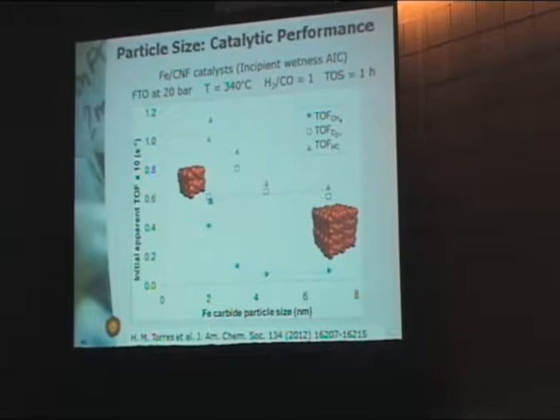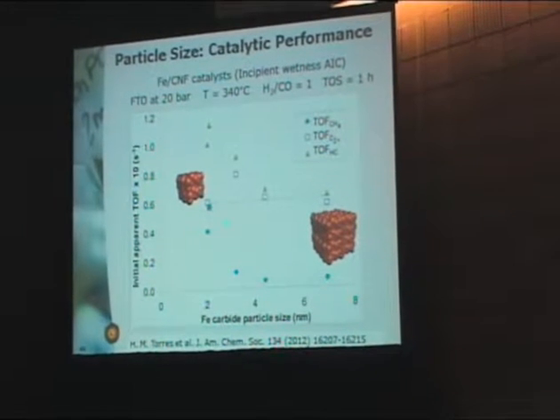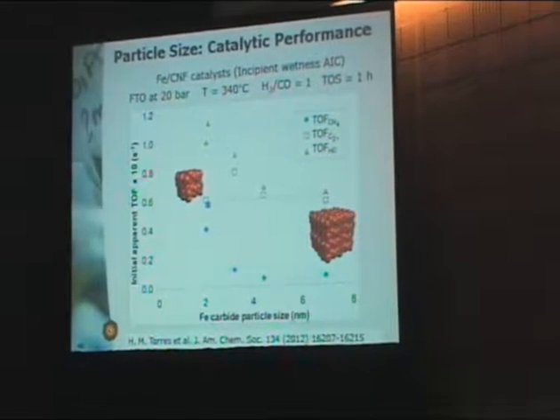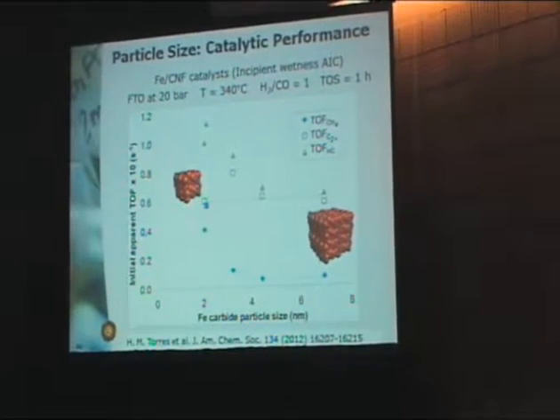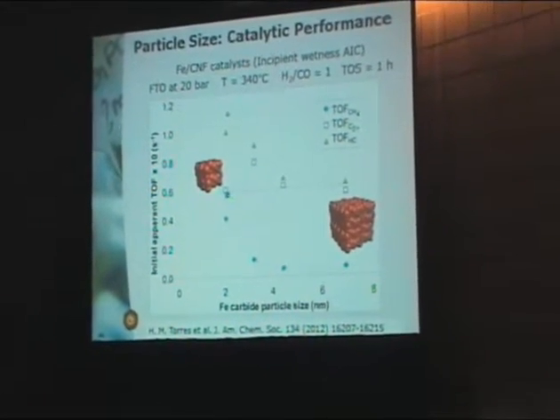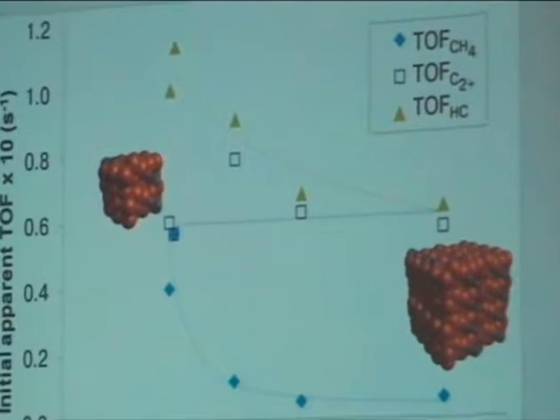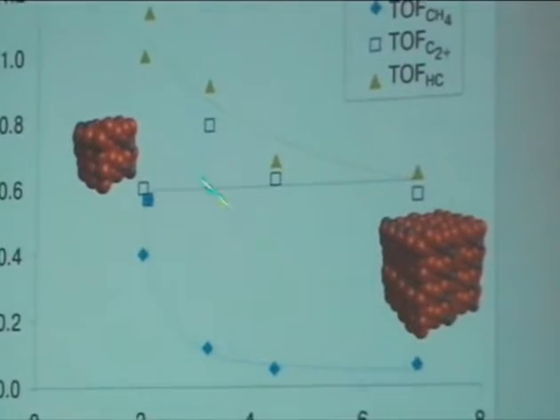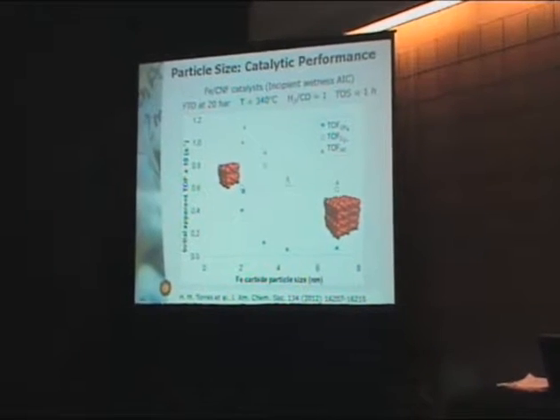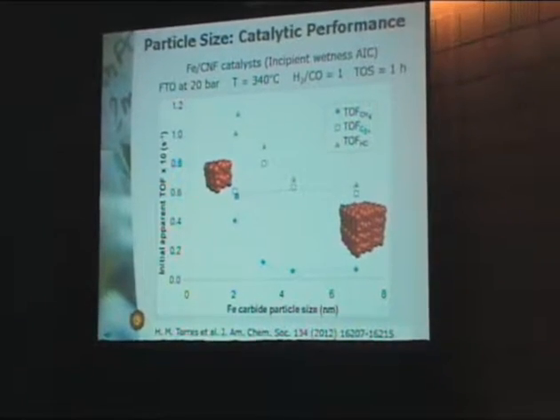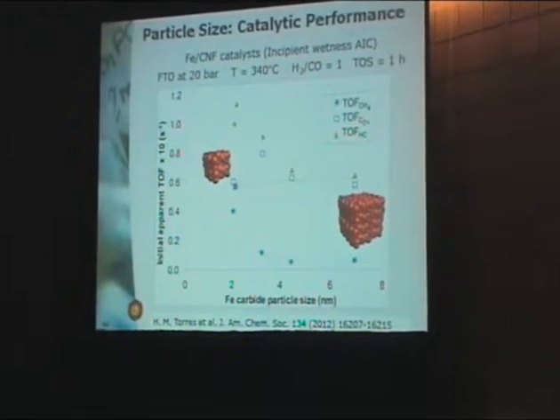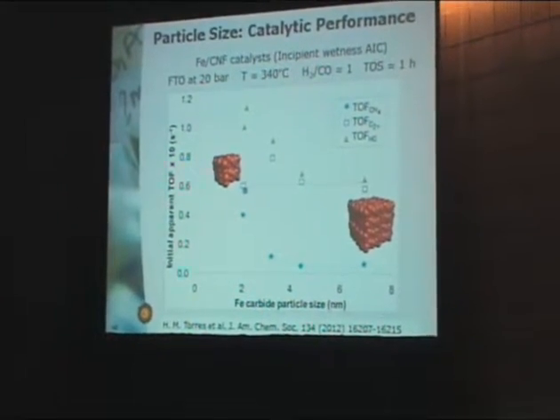However, it goes up only for the methane. The methane turnover frequency, as indicated here, goes up steeply, while the turnover frequency for C2 plus products is constant. So it's a clear design parameter, you might say. We want particles that are sufficiently large in order to prevent the contribution of more methane than necessary, you might say.